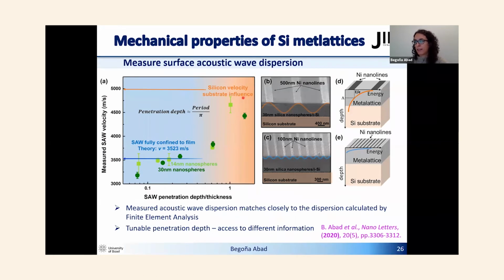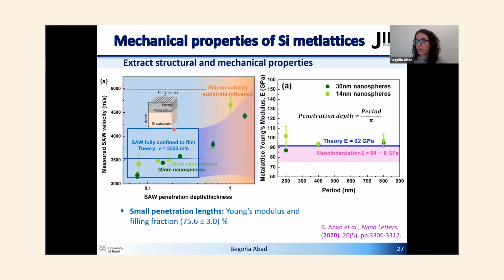And we have this trend that can be explained as a function of the penetration depth, because for sufficiently large penetration depths, we recover the speed of sound of the silicon, which is around 5,000 meters per second. But if we are able to confine the wave sufficiently, we are able to recover the velocity of the metalattice. This is calculated from finite element analysis, and we see how when we have the waves totally confined, we recover this value. This tunable penetration depth allows us to access different information. From the very confined acoustic waves, we have access to the properties of the metalattices.